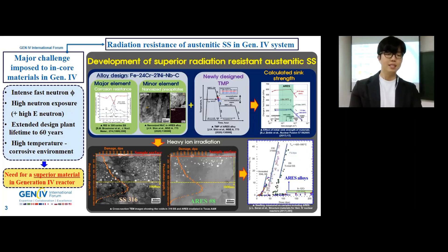However, these materials have been known to be susceptible to DBTT, which causes lower fracture toughness and brittle fracture at room temperature. Moreover, most FM steels have lower high-temperature oxidation resistance compared to austenitic stainless steel. Austenitic stainless steel has also been extensively used in the past as a first candidate material for sodium fast reactor hexagonal wrapper tubes. However, poor swelling resistance is one of the reasons why austenitic stainless steel was limited in Gen 4 systems.